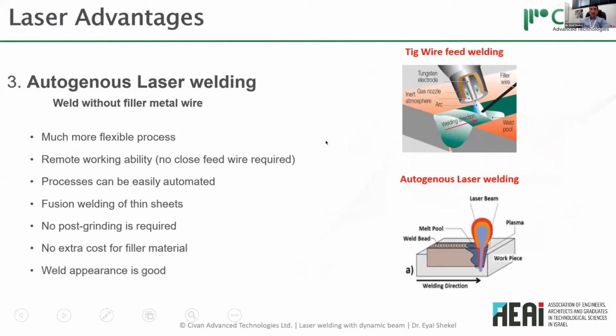Another advantage is the ability to do welding without a wire. So if you compare here to TIG welding, where you have the filler wire, in laser welding you can do the welding without the filler wire. So that gives you a much more flexible process because you don't have to make sure that the wire gets to the right place and you don't have to feed the wire. So you can do remote operation. The process can be easily automated. You can do welding of very thin materials where there's no room to add a wire, and there's no post-processing needed after the weld.